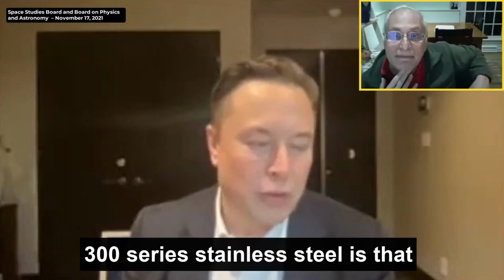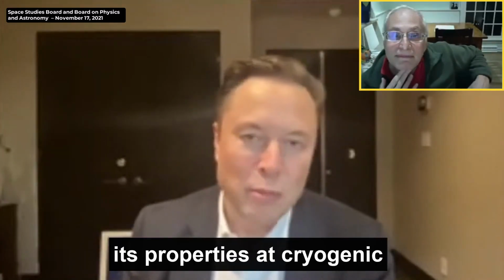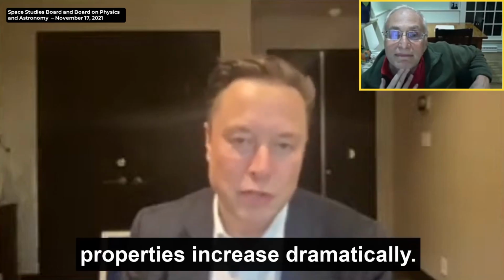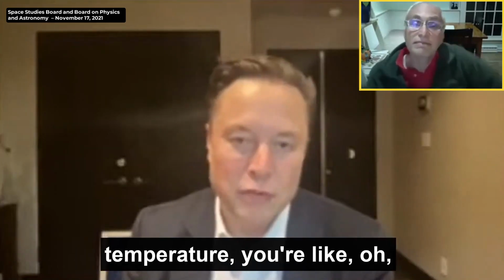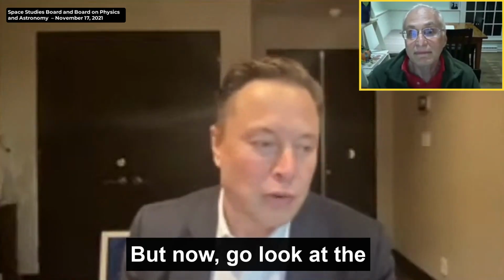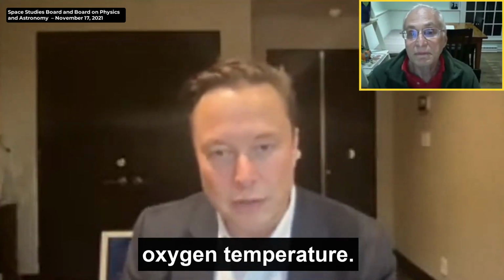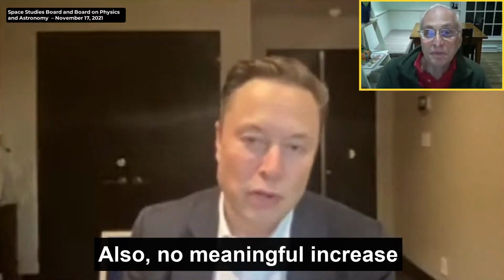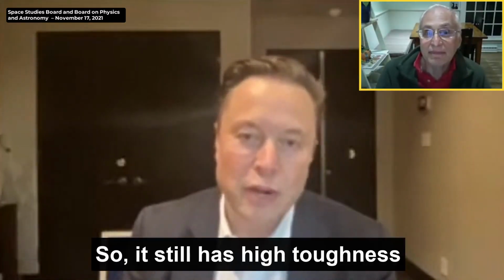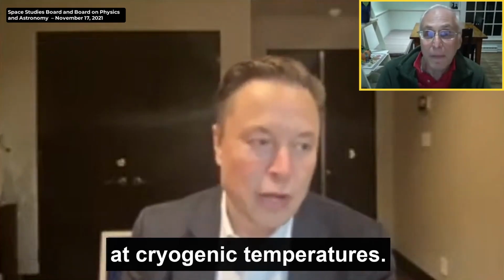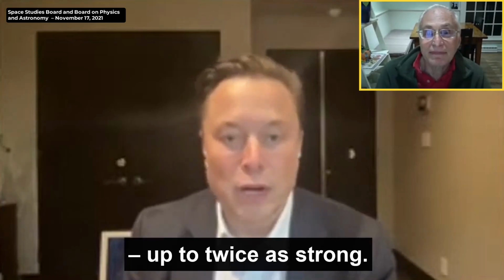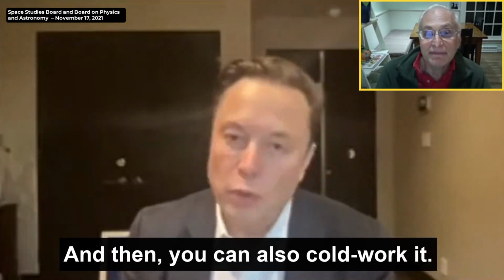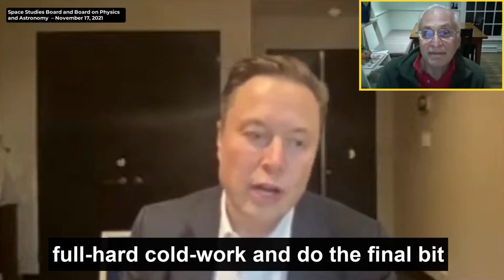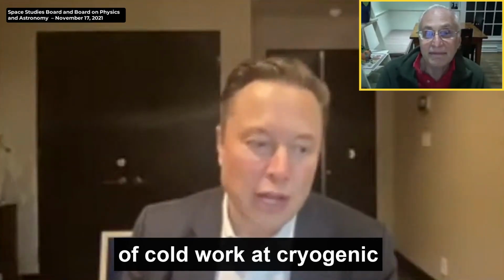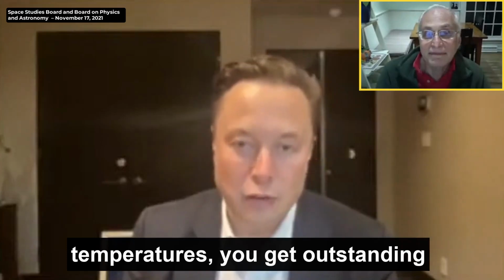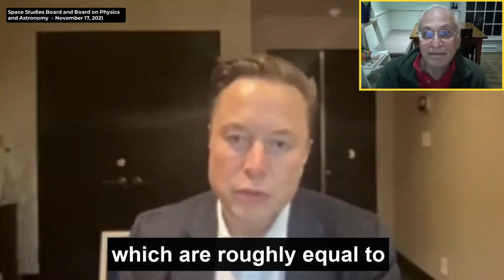The interesting thing about 300 series stainless steel is that its strength properties at cryogenic temperatures increase dramatically. So if you were to look at the material properties at room temperature, you'd be like, oh, it's not that great. But now go look at the properties at liquid oxygen temperature. Oh, actually much stronger. Also no meaningful increase in brittleness. So it still has high toughness at cryogenic temperatures. It is much stronger, depending on how cold you go, up to twice as strong. And then you can also cold work it. So if you go full hard cold work and do the final bit of cold work at cryogenic temperatures, you get outstanding strength properties, which are roughly equal to an advanced carbon fiber.